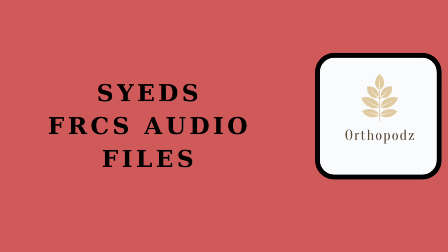Type: low viscosity, long doughy phase. Medium viscosity reaches doughy stage later than high viscosity, and high viscosity has a short doughy phase. Optipac is a closed vacuum system. Simplex is a medium viscosity, high fatigue strength, and low creep, that is plastic deformation. It has 1 gram tobramycin in it. Palacos is a high viscosity, green dye, shorter waiting period, and extra long working phase. It R plus G has gentamicin in it.